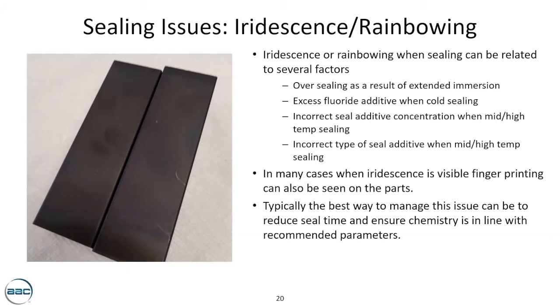You can see in the picture that with iridescence, there is even visible fingerprinting on the parts. Typically, the best way to manage this issue is to reduce the seal timings or to ensure that the chemistry is being used at the recommended parameters.